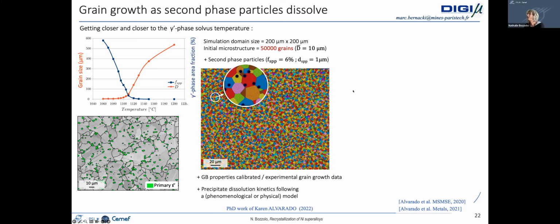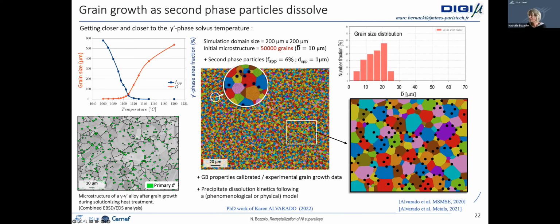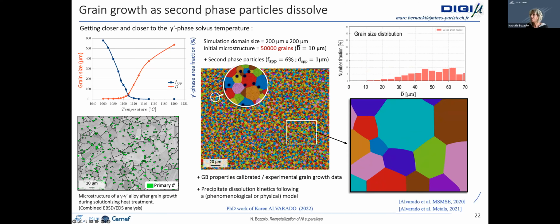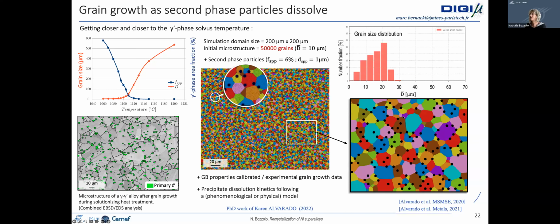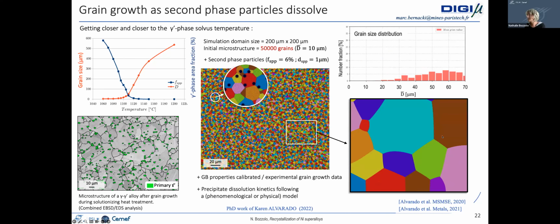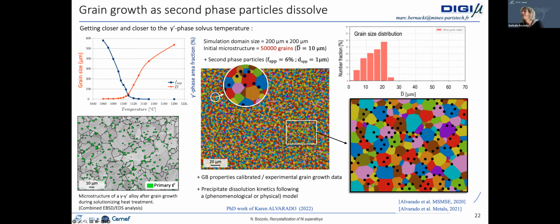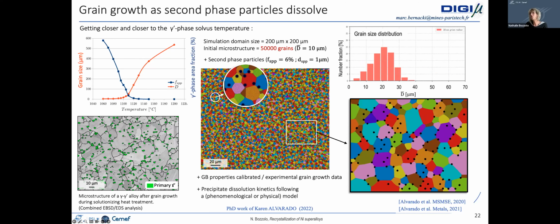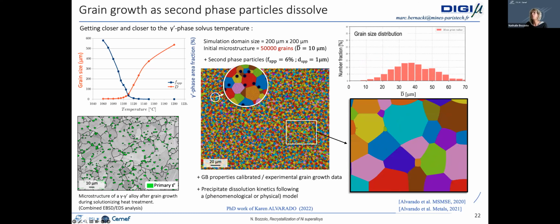And then the simulation, so I show you here a zoom of the simulation because the domain was too big. So here you see the grain size distribution. As long as you have enough second phase particles, grain growth is limited, and you see that grain growth starts and accelerates along with the dissolution of the second phase particles. So this works quite well. So Smith-Zener pinning is indeed very useful, well-known, well-described, and applied notably in these alloys.